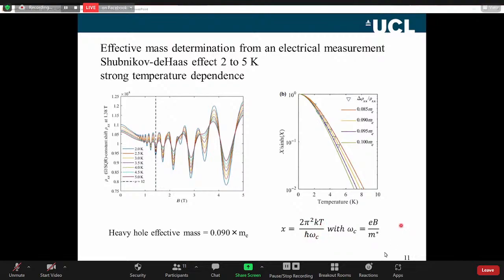Cyclotron frequency is related to mass. How this thermal damping term changes with temperature is a good measure of the effective mass of the carrier. We found that the effective mass is about 0.09 times the electron mass. It's a heavy hole, but it's a very, very light heavy hole, which is very good for transport.